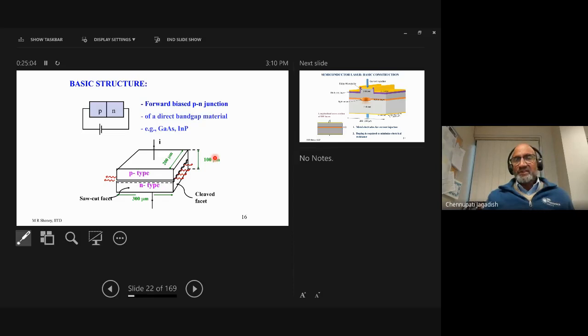So what will happen in the case of this laser? You create a PN junction, which means you dope the semiconductor with a P-type dopant and an N-type dopant, for example in gallium arsenide or indium phosphide, both of which are direct band gap semiconductors. For P-type doping, we use either zinc or beryllium. If you're using MOCVD growth, metal organic chemical vapor deposition, you typically use zinc. If you're using molecular beam epitaxy, you use beryllium. They both come from group 2 of the periodic table, so you've got a missing electron, and that's where you create the P-type, the holes, and the positively charged part of the semiconductor.